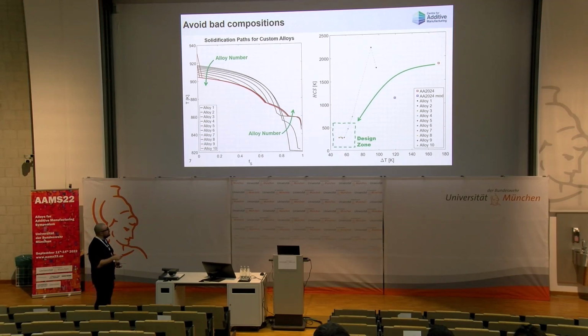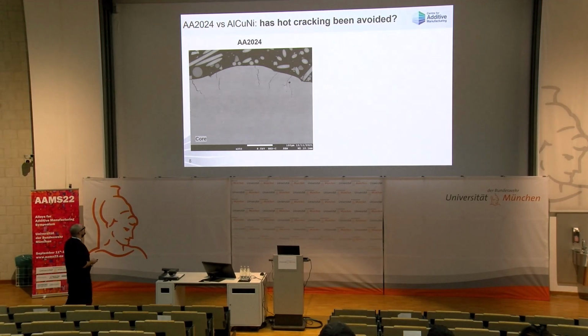So we discard the first 3 compositions, and we're working in this area only. For the rest of this talk, I'm going to compare 2024 with our custom alloy. 2024 is a hot-crack-susceptible alloy, but if you want to isolate this, a very good way, in my point of view, is to produce the alloy without cracks, and you can do this by acting on process parameters. It's not easy, but you can do it.